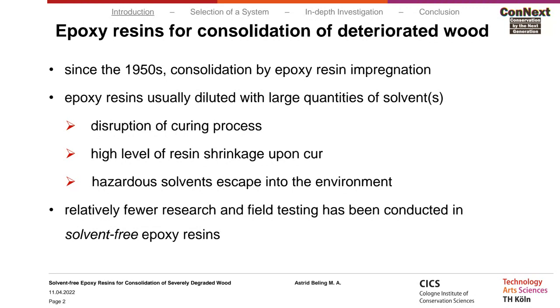Unfortunately, there are still many prejudices against epoxy resins, and this is probably because previous studies repeatedly selected the same high viscosity and reactive products, and they were diluted with large quantities of solvents to reduce the viscosity and the reactivity. But that brought disadvantages like a high level of resin shrinkage upon cure or disruption of the curing process.